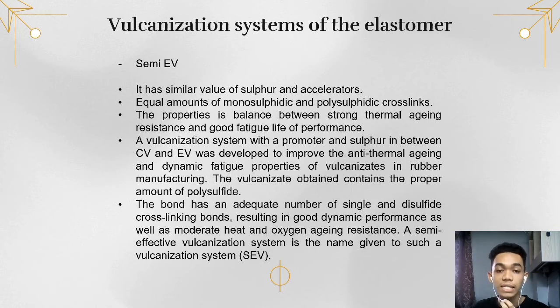A vulcanization system with a promoter and sulfur in between CV and EV was developed to improve the anti-thermal aging and dynamic fatigue properties of vulcanizate in rubber manufacturing. The vulcanizate obtained contains the proper amount of polysulfide. Lastly, the bond has an adequate number of single and disulfide cross-linking bonds, resulting in good dynamic performance as well as moderate heat and oxygen aging resistance. A semi-effective vulcanization system is the name given to such a vulcanization system, which is SEV. That's all from me. Thank you.